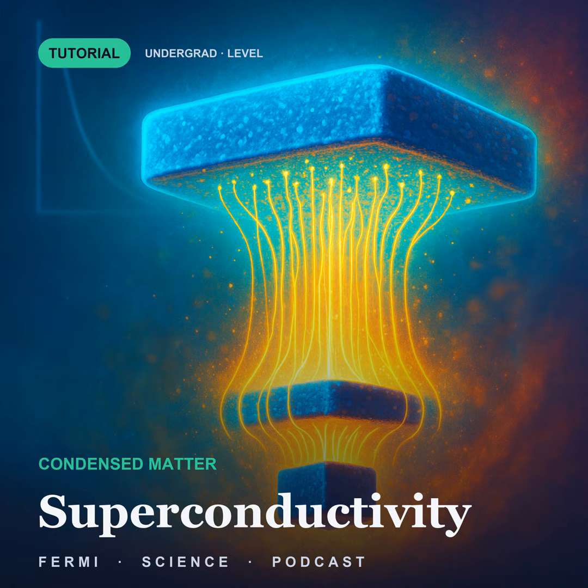What am I picturing? Start with which electron pairs with which, because it is not arbitrary. 2 constraints pick it out, and both are about counting. If a pair is to have any freedom to scatter into other pair states, and that scattering is the attraction doing its work, then all the pairs must share the same total momentum. And the choice that maximizes how many partners are available is 0. So a pair is an electron with some momentum and an electron with exactly the opposite momentum, 2 points on the Fermi surface directly across from one another. Opposite spins as well, up with down. Antipodal partners. Every point on the surface married to the point diametrically opposite. And every one of those marriages has the same total momentum, namely none, so they can all exchange partners with each other freely. And the spins are opposite because both electrons are in the same orbital state, which Pauli permits exactly once. That is the picture.